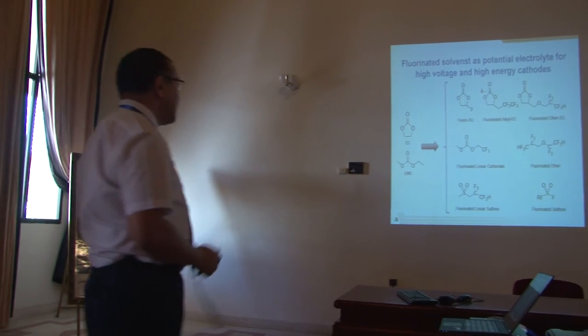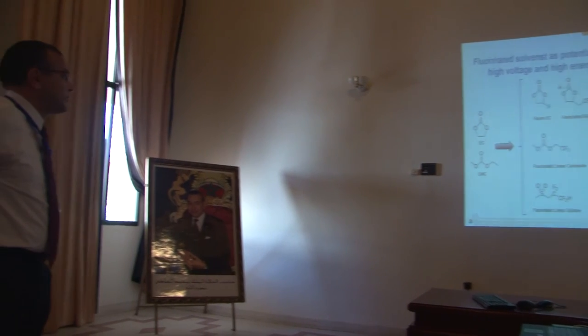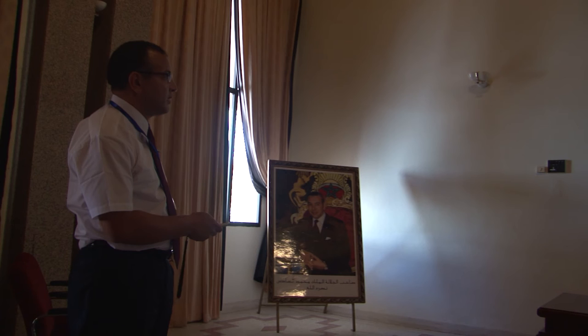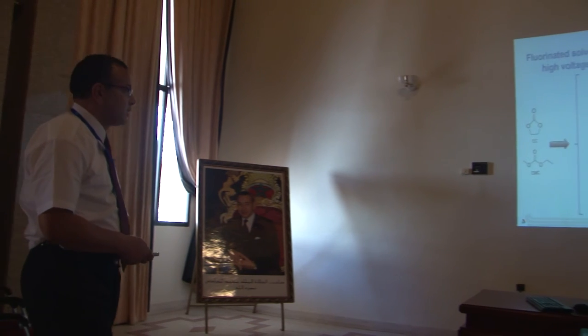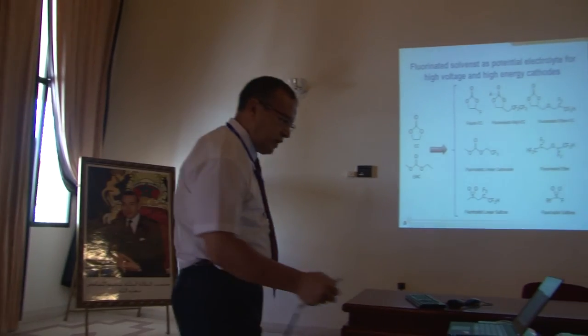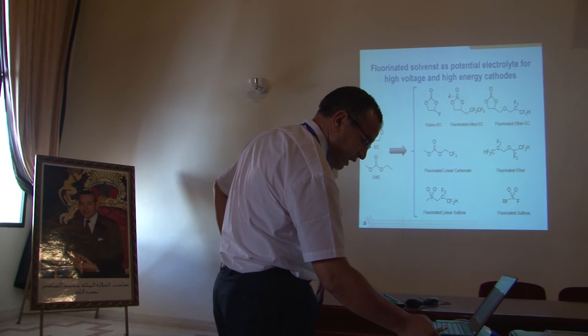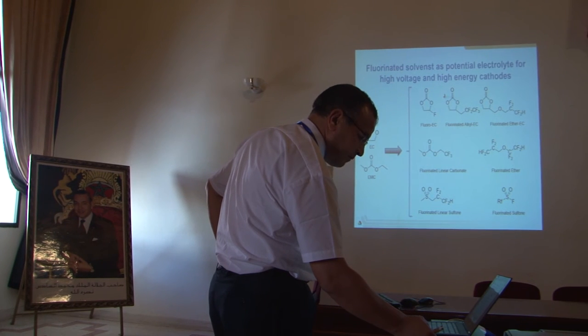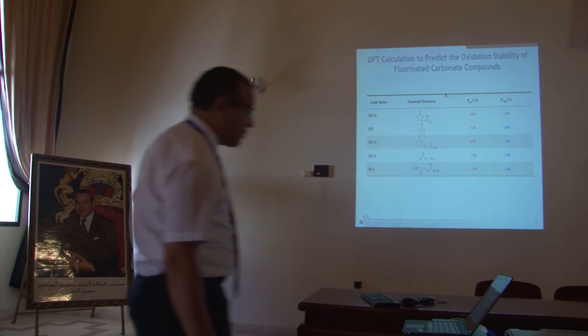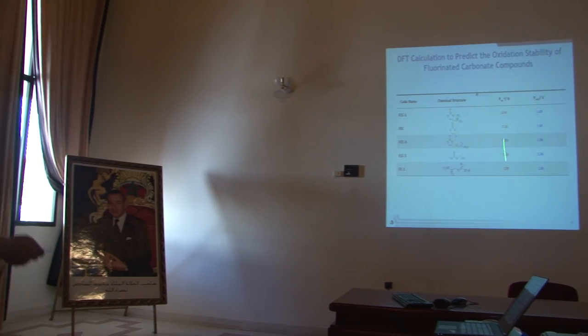So we've been looking at different fluorinated solvents as potential solvents for high voltage electrolyte. So we have all kinds of fluorinated solvent, either ether based or alkyl based or cyclic and linear based or even sulfone based. And as Emilio mentioned, we do have a supercomputer that does a lot of DFT calculation. In this case, my colleague Larry has done some calculation that shows that this fluorinated solvent has very high tolerance to high voltage, for instance.